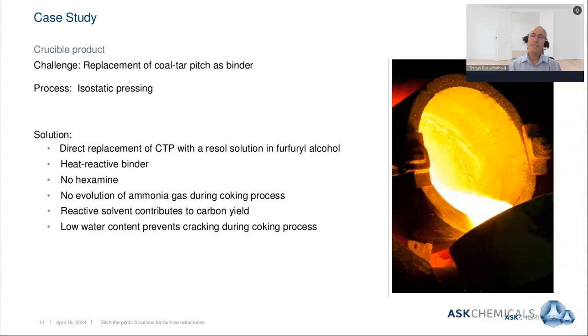We'll first look at a case study that we had recently where we replaced coal tar pitch as a binder in crucibles. In this case, crucibles made by the process of casting followed by isostatic pressing, or as some people may say, continuous casting and then isostatic pressing. In our case, we used a direct replacement of the pitch by a resol, a phenolic liquid resol, dissolved in furfuryl alcohol as a reactive solvent.